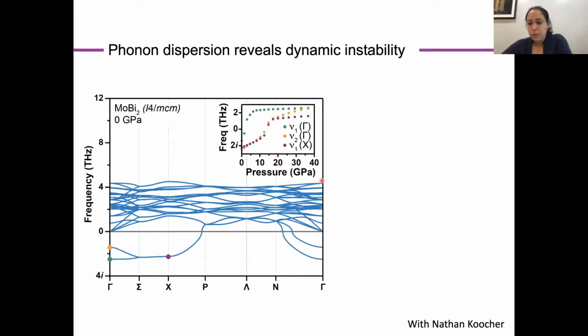And so once again, in partnership with Nathan Koocher from the Rondinelli lab, we interrogated the dynamic properties of this material by looking at the phonon dispersion diagrams. In comparison to the thermodynamic properties that I was showing you at the beginning of this talk, this looks at how small changes in atoms and lattice influence the potential energy surface. And so what Nathan found was that while our high pressure molybdenum bismuth 1-2 structure is dynamically stable, as he decreases the pressure in his computations, he introduces multiple points of instability at multiple points of our decompression. And indeed, by the time we get to the hypothetical version of this structure, we now see multiple imaginary phonon frequencies, helping to explain why we don't recover this material to ambient conditions.